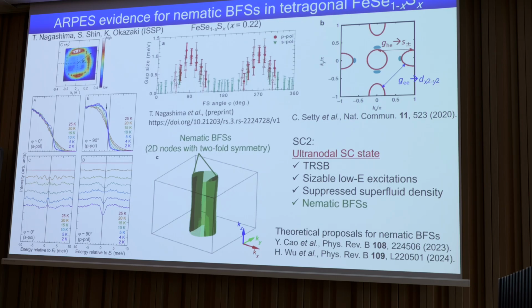But surprisingly, this SC2 region is outside the nematic QCP, meaning that it's a tetragonal system. Indeed, if you look at the Fermi surface above TC, you find a C4 symmetric Fermi surface. But for some reason, this gap anisotropy has a twofold symmetry. So we call this nematic Bogoliubov Fermi surfaces.